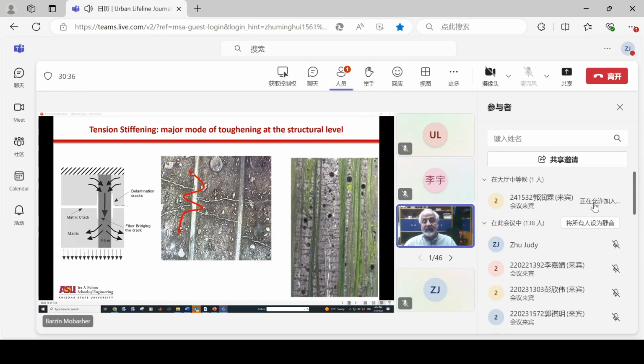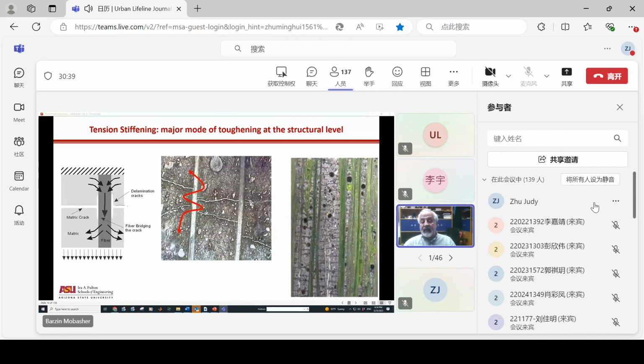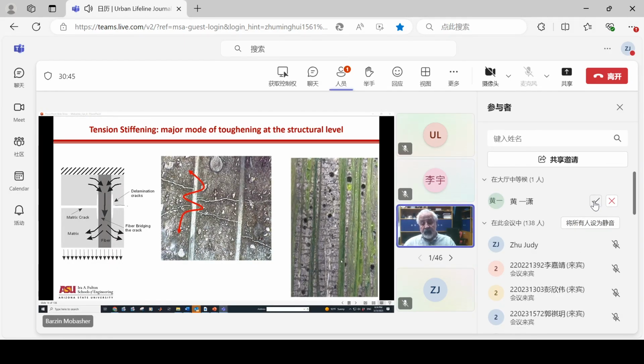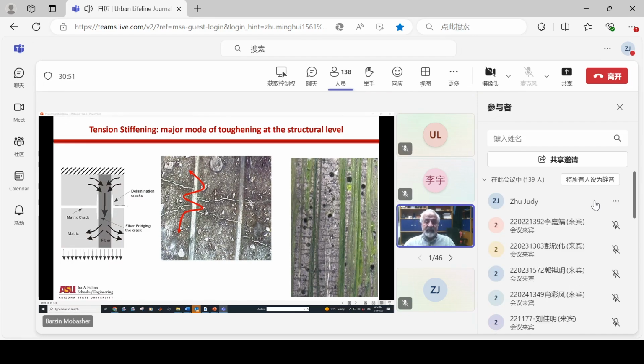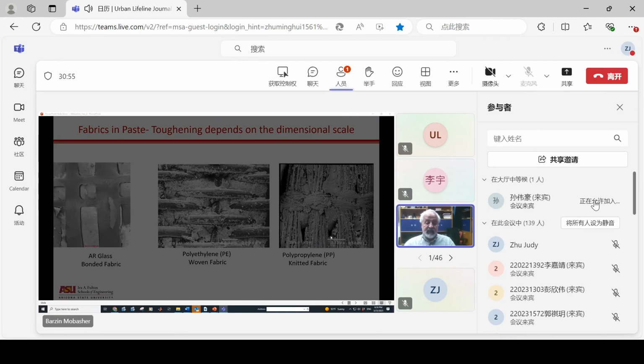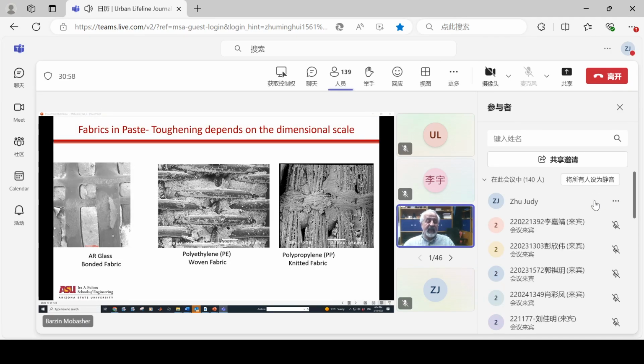So any way we can do this would allow us to generate this parallel cracking. The spacing between these cracks is now on the order of 0.5 millimeter. So the crack width is kept smaller. The cracks cannot open up, so more cracks are forming, and so the bond issue becomes extremely important. That takes us into this area of manipulating the microstructure to make textiles with AR glass and polyethylene, woven. Polymeric materials don't have a good bond system, but if we can make these geometrical changes in the shape, like textile manufacturing specific for our areas, they become extremely wonderful.